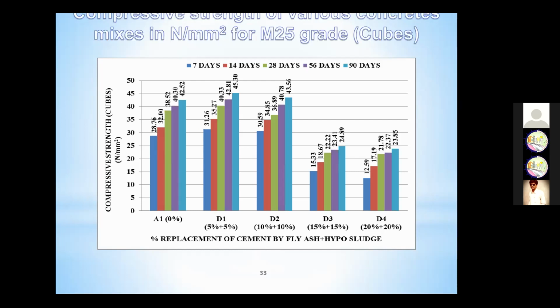I have omitted the results regarding the fly ash class F only concrete and the cement replacement with hypo sludge only, that is, the B series and the C series. Due to the time constraint, we go directly to the 50% hybrid mix. You can refer to the standard concrete, 42.52 at 90 days. But with D1, 5 plus 5%, fly ash F 5% and hypo sludge 5%, you can see 45.30 strength at 90 days.